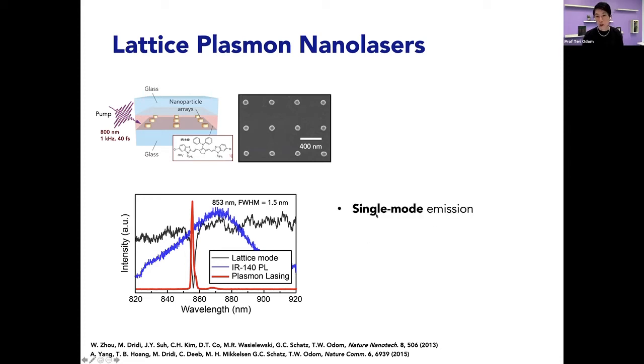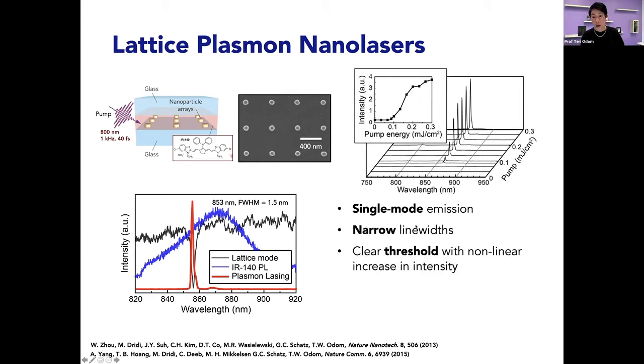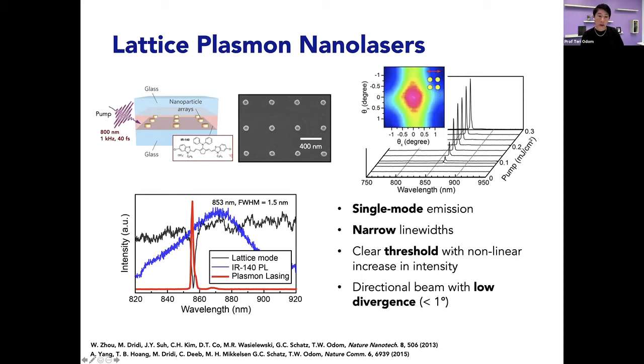So we're able to achieve single mode emission sort of by design. There's a very high local optical density of states. This is at the gamma point, coming normal to the surface. The linewidths are quite narrow. There's a clear threshold with a nonlinear increase in intensity. We have a beam that we can manipulate in the far field, and the divergence is quite low.